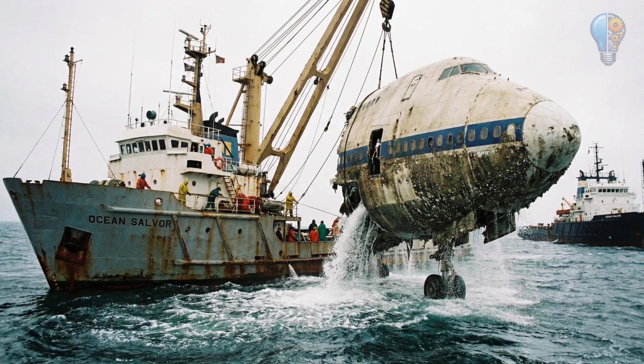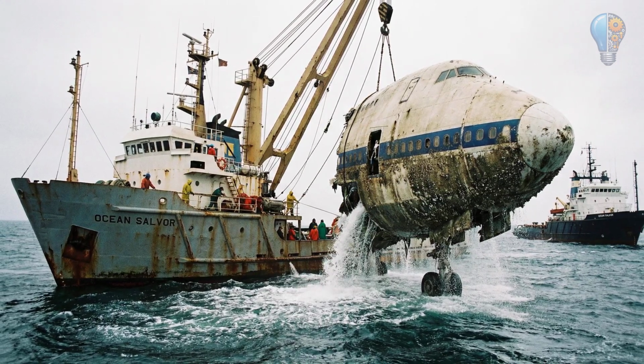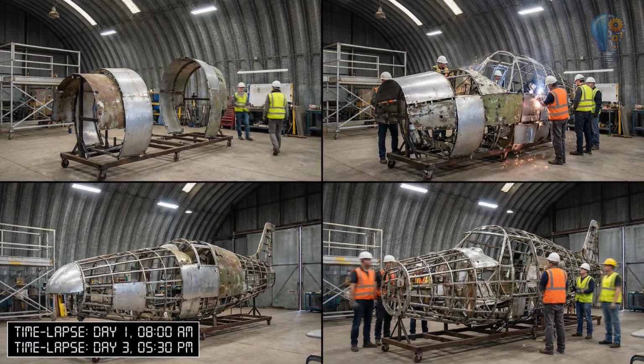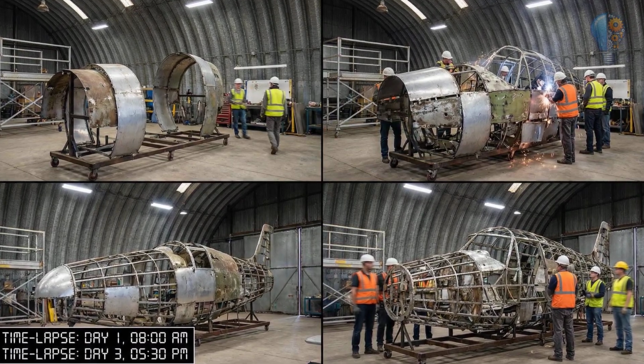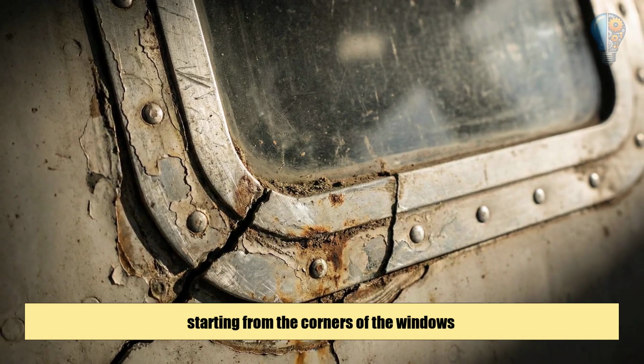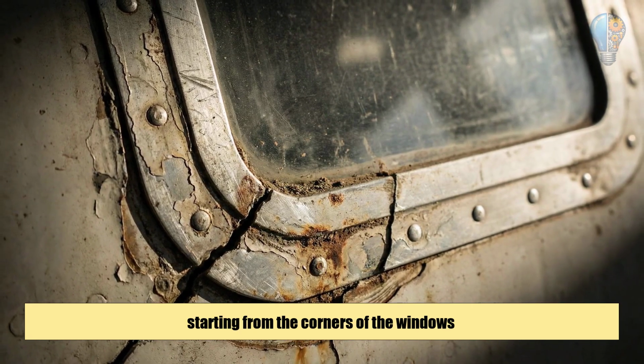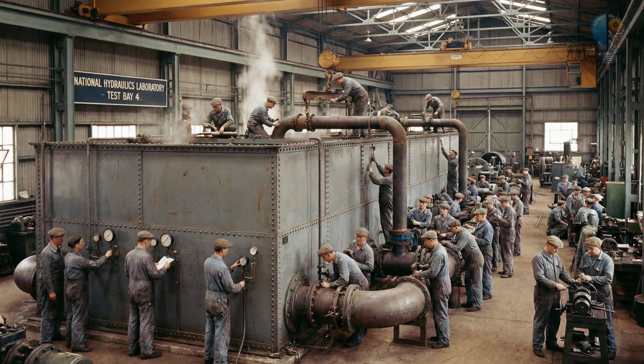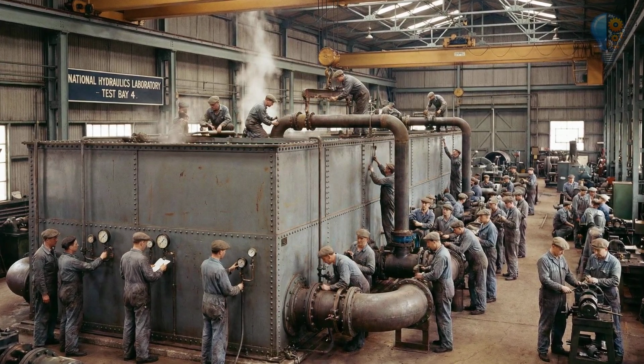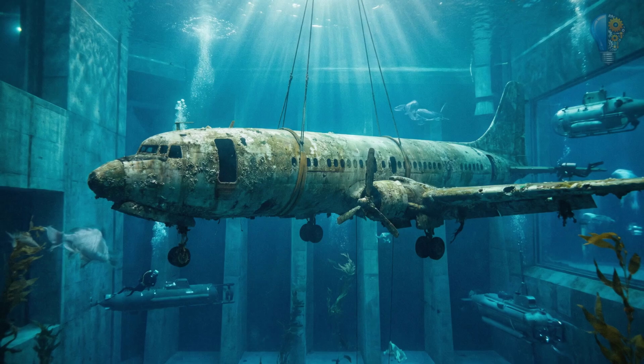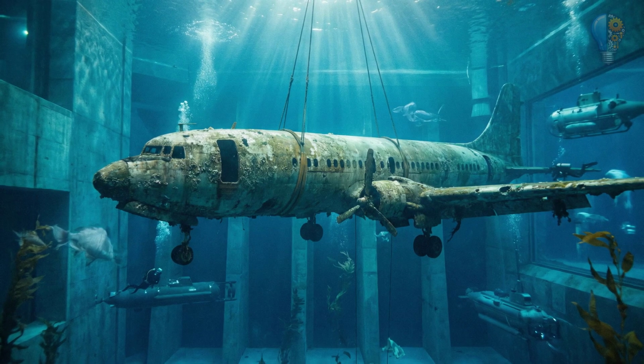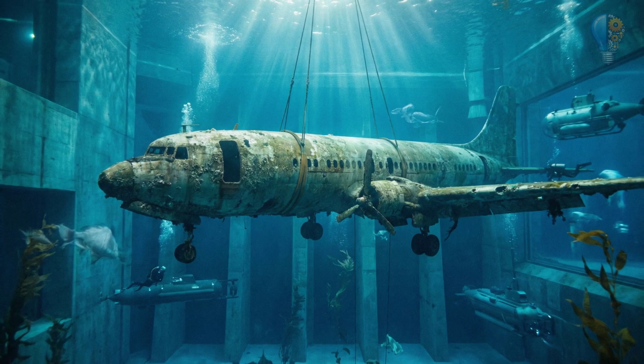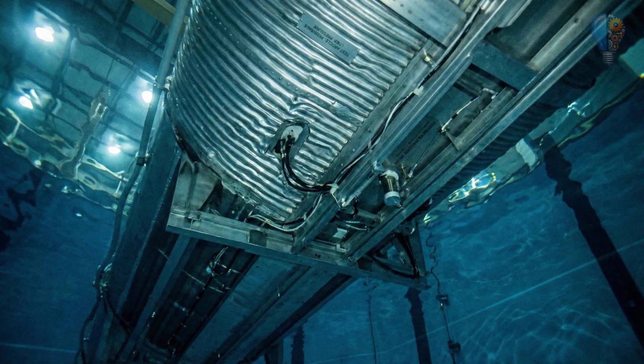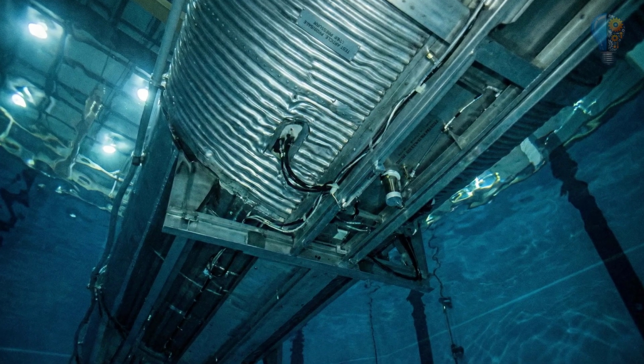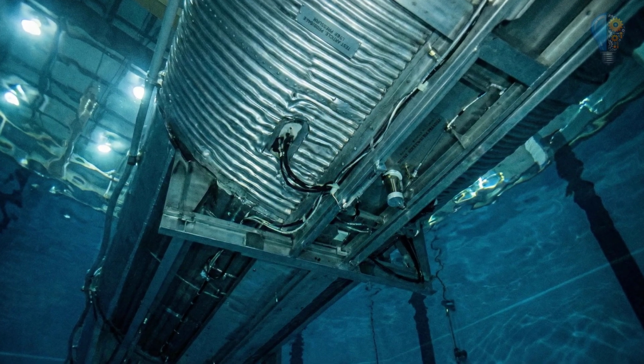They recovered wreckage from the ocean floor and painstakingly reconstructed the aircraft like a giant jigsaw puzzle. They found that the fuselage had torn apart starting from the corners of the windows. To confirm their suspicions, they conducted an unprecedented test. They took a complete Comet fuselage and placed it in a massive water tank, then subjected it to repeated pressurization cycles, simulating takeoffs and landings over and over again.